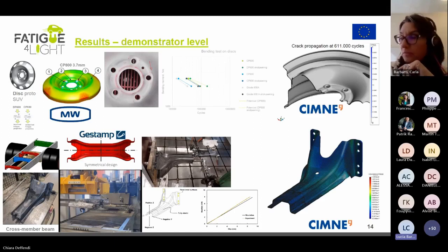And after that, ideally, you would have been able to see some simulations which were performed by CRF at system level and by CIMNE at component level, where you can see the failure mode. This time this is the misuse test, so it's just monotonic loading, and the fatigue testing is currently underway, let's say. Then on the lower part of the slide, we have the same demonstrator envisioned, so the lower control arm,